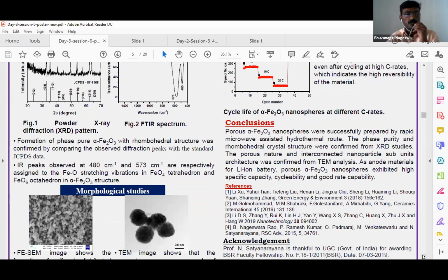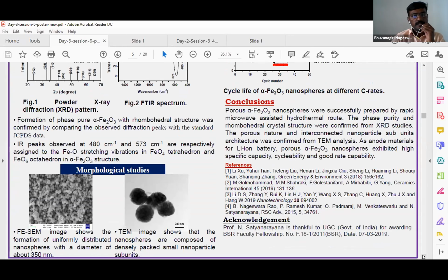We confirmed the hematite phase and the crystal structure by comparing the XRD pattern with the standard JCPDS data. Also, we estimated the average crystallite size using Scherrer's formula, which is found to be approximately 28 nanometers. Further, the structural coordination is confirmed by FTIR analysis. You can see here IR bands observed at 480 and 573, which are respectively assigned to Fe-O bonds in the FeO4 tetrahedron and FeO6 octahedron.